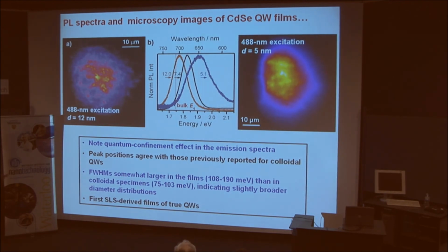Okay, here are some emission spectra that were collected from these films. This is the emission energy for bulk cadmium selenide. And this is the emission feature for 12 nanometer diameter wires, 7, which is blue shifted, and 5, which is even more blue shifted. And these peak positions are right where they should be for wires of the diameters that we grew in colloidal dispersion. So I submit to you that these are the first SLS-derived films of true quantum wires. They are exhibiting the quantum confinement effect, and that's not been previously demonstrated.